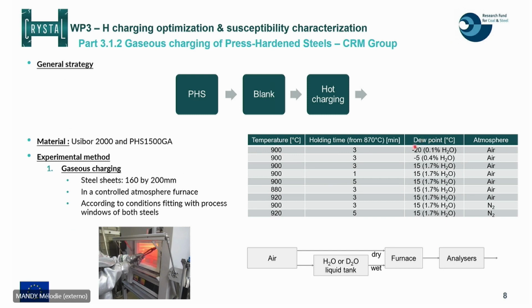So firstly, the dew point. The dew point was varied from -20 to +15 degrees Celsius. The dew point is actually an image of the humidity that you can find in the atmosphere of the furnace. That's why you have the conversion into percentage of water just next to the dew point. So the higher the dew point, the wetter the atmosphere in the furnace. And another point that we made vary is the carrier gas. In most conditions, we worked with air, but we worked also with nitrogen. So you will see why just after.